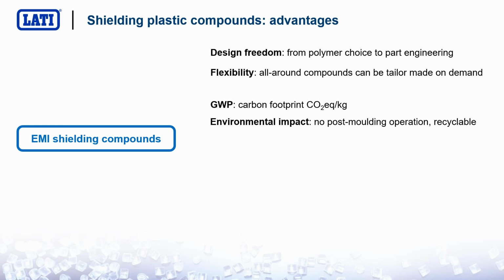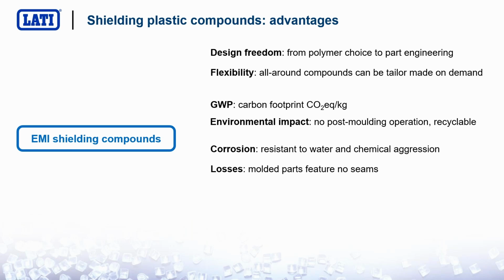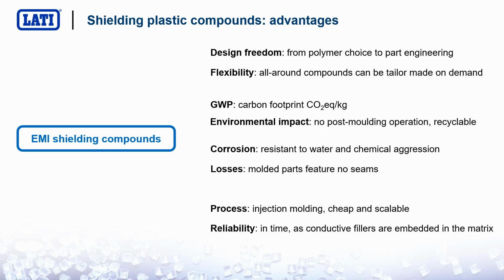There are no post-molding operations, so you need no painting, no degating, no deflashing, nothing. The part pops out of the mold, finished and perfectly shielding. Corrosion resistant, of course, because plastic does not suffer from corrosion. Molded parts have no seams, so also from a losses point of view, EMI shielding plastic parts can be extremely effective and with full potential. The process in itself, injection molding, is very straightforward, easy, cheap, and reliable in time. Don't forget that conductive fillers are embedded in the plastic matrix, so they are protected from any kind of environmental issue.